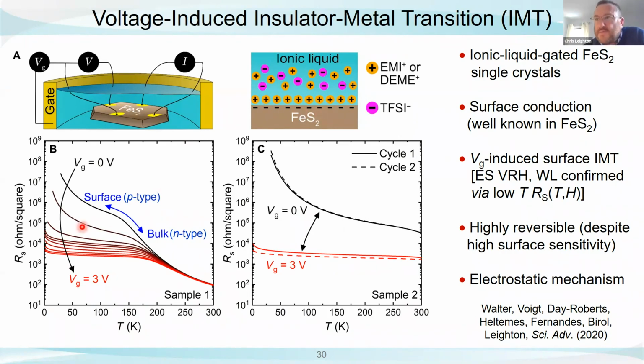And there's a bit of a wrinkle with the transport in this material in that it exhibits surface conduction. So when you look at resistance as a function of temperature, there's this crossover, a little bit like a topological insulator, between the bulk conduction, which is N-type, and a surface shunting, which is P-type. But just ignoring that, it is literally a distraction. What happens when we apply positive voltage is we can drive this beautiful insulator-metal transition. So we're adding electrons here, driving it to a metallic state. And I should emphasize, we can apply 3 volts, go back to 0, 3 volts, go back to 0.